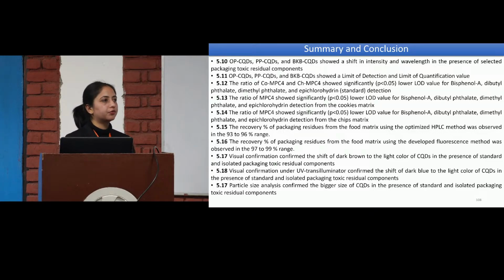Then the recovery percentage of the packaging residue from the food matrix using the optimized HPLC method was observed in the range of 93 to 96%, and the recovery percentage of packaging residue from the food matrix using the developed fluorescence method was 97 to 99%. And after that, we confirmed visually the shift from dark brown to light brown color in the presence of the standard and isolated packaging residues.